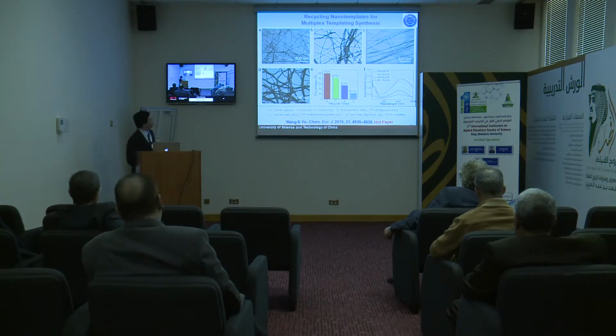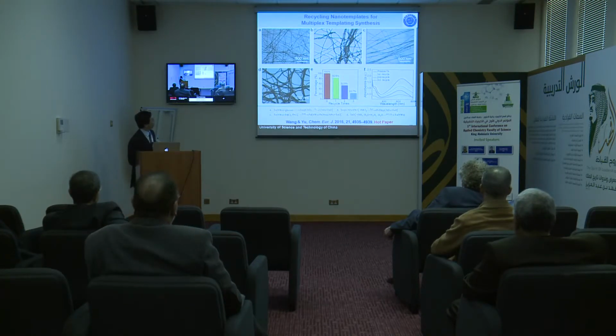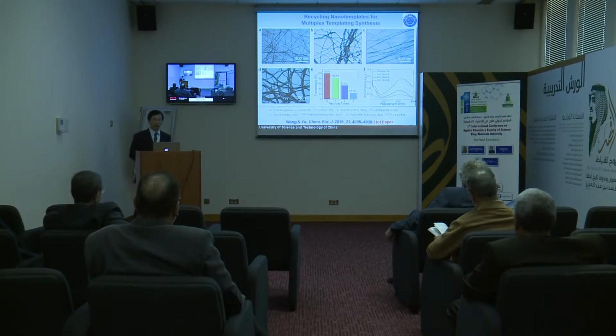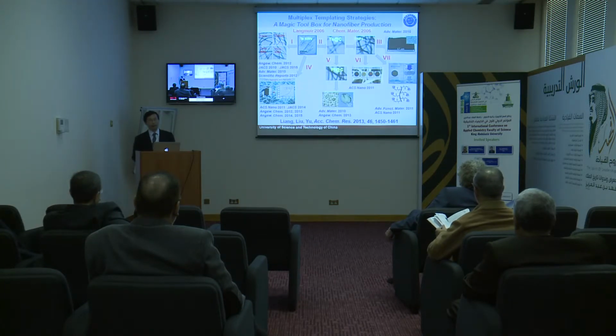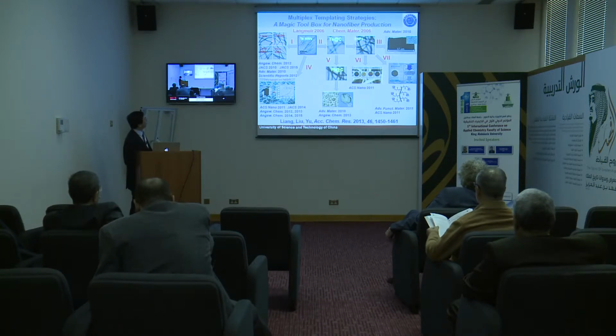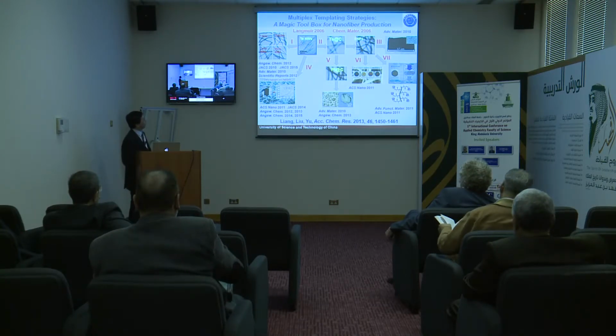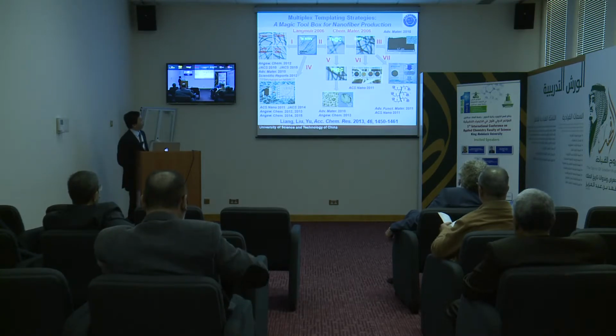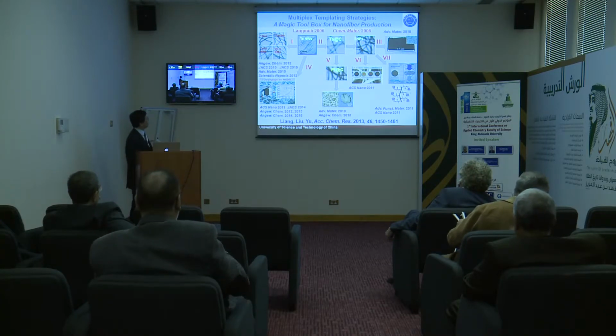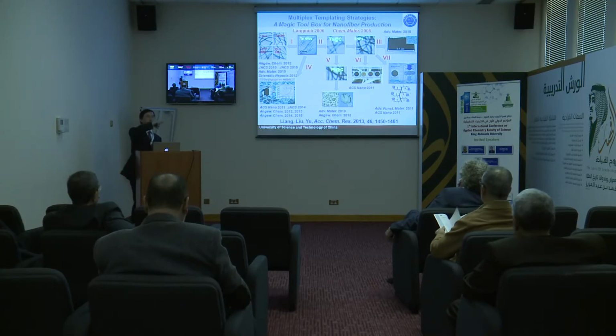Here is some data showing recycled nanowires. Indeed, they still keep a very good quality. They have a high aspect ratio, and their diameter is also very uniform. So this is a good way: we start from these tellurium nanowires, which we can synthesize at scale, and then you can do many things. You can do chemical transformation. You can use them as a physical template. You can access different kinds of nanowire systems, so that you can do this scale-up synthesis. You can get a very giant nanowire network in the future.